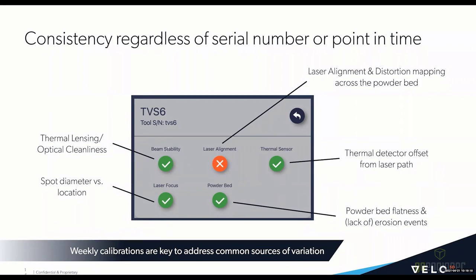This is basically verifying that the optical train is clean. And if there exists debris on the optical train, then the spot will move as the optical train heats up. The debris will heat up and cause variation with respect to time and temperature. So we verify for that with beam stability.